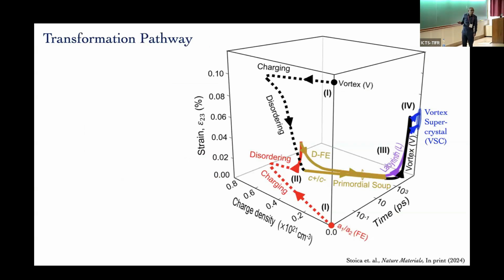I like this diagram because I came up with it. So time over 7 orders of magnitude, charge density, what you're pumping, one particular value of strain, shear strain, that lets you roll, all of these things roll up. So I like that particular component. So you start here at 0 time and 0 charge density, and there are 2 phases, mishmash, this one and this one. Both of them, you hit them with a pulse, boop, boop, boop, forms the soup, and then out comes the crystal over here.